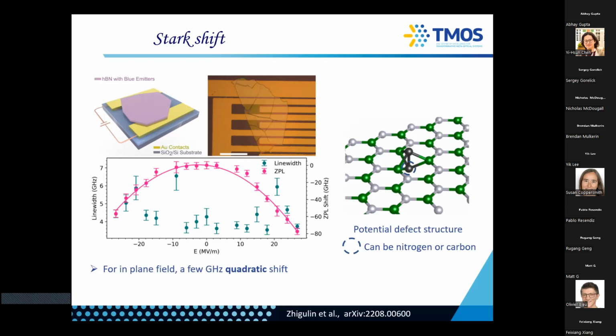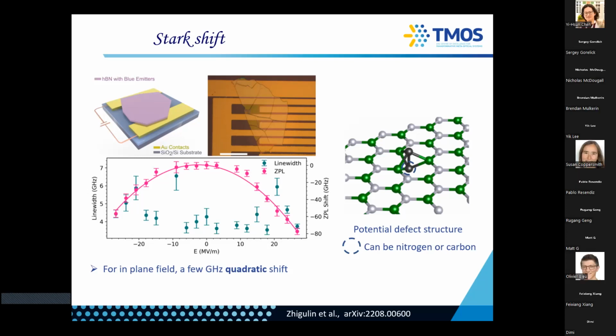One way to address this is really to do isotopically pure carbon, and then look at some more signatures, hopefully some hyperfine if you can see it. The other thing I will add here is that because we only make them in this carbon-rich hBN, our, not hypothesis, but we lean towards the carbon rather than the nitrogen. And finally, I should say that people also modeled a lot about only a single carbon atom, because in principle, you could have a single substitutional carbon atom, which is an optically active defect. But in hBN, these carbon atoms are unstable, so they will cluster up straight away, even at room temperature. So both CB and CN would not be a stable impurity in hBN with an optical line.